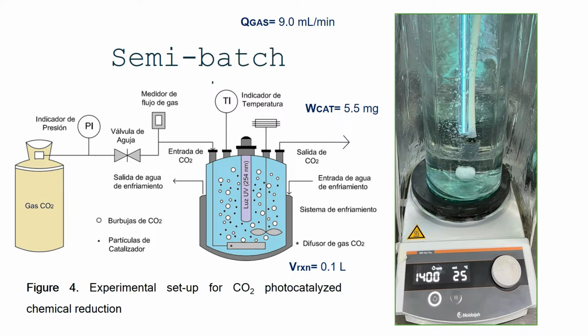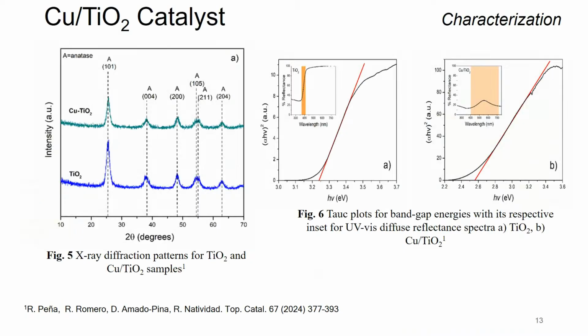If you input a lot of gas, or the convection is higher, the residence time is lower, and then the CO2 concentration in the solution is low. So be careful with this. It's a very important variable. So the flow that we are applying is only 9 milliliters per minute. So these are the results of the characterization.